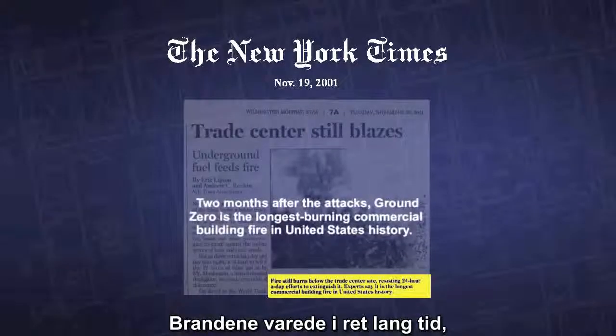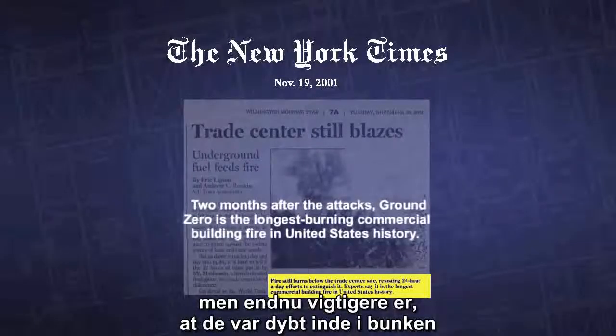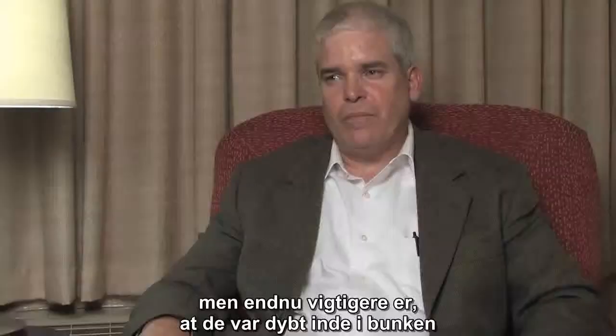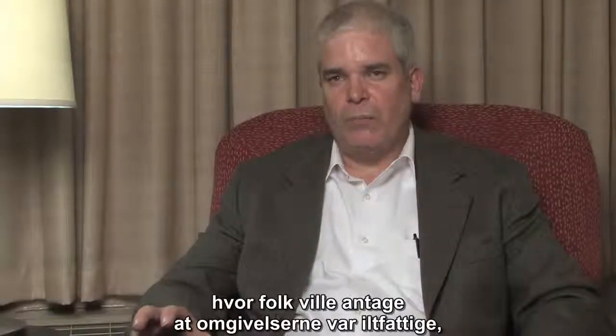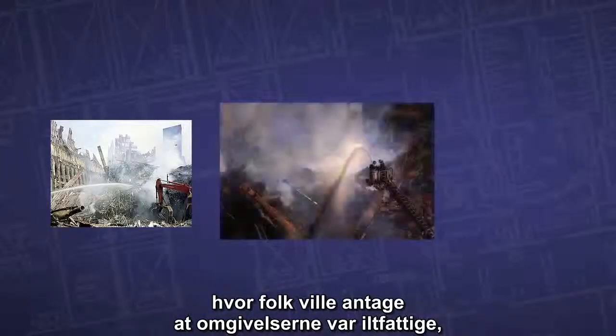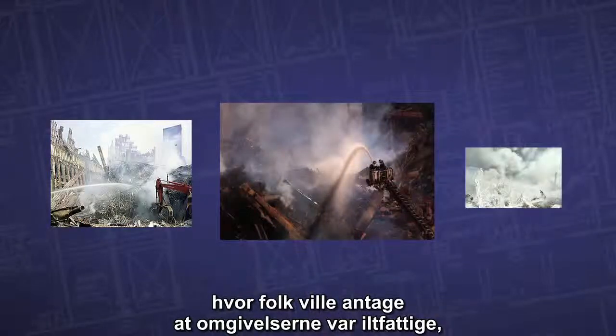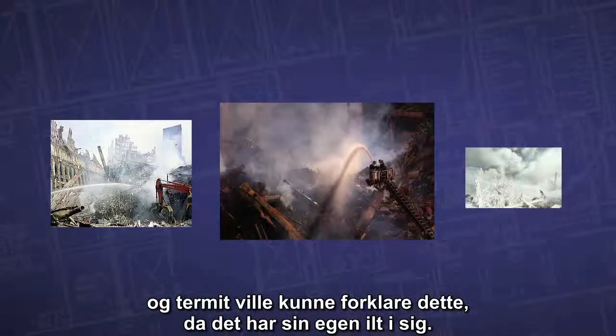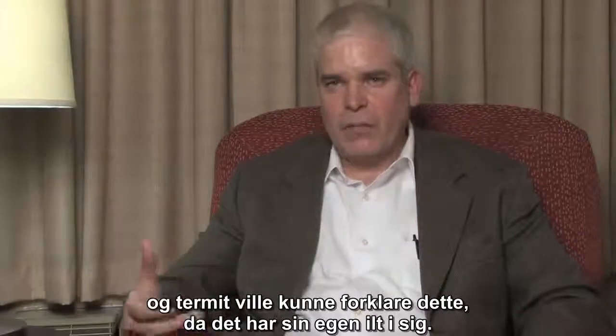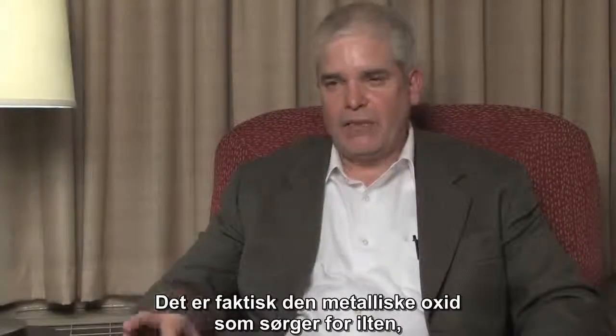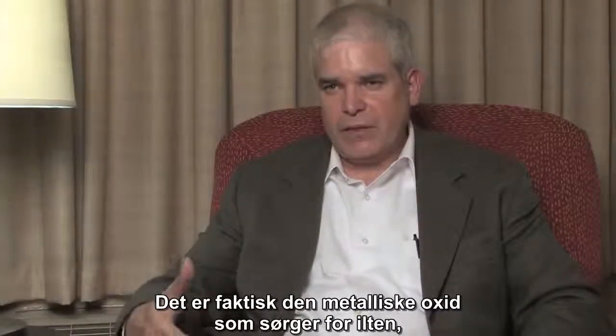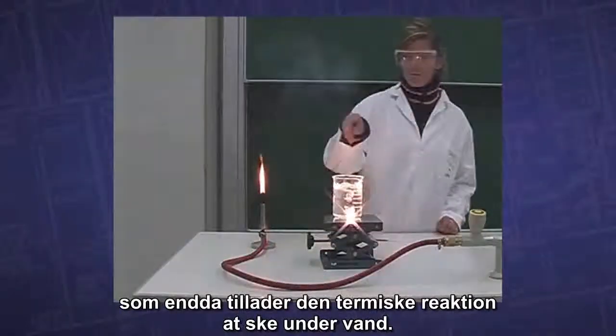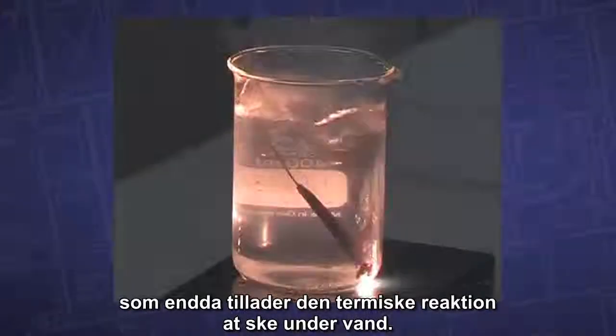The fires lasted for quite a while, but most importantly, they were deep within the pile, where people would expect that the environment was oxygen starved. And thermite could explain this because it has its own oxidant within. It's actually the metallic oxide that provides the oxidant to allow the incendiary thermite reaction to occur, even underwater.